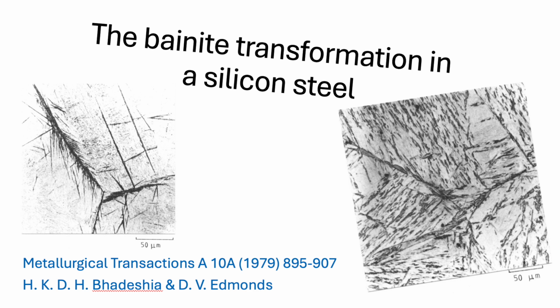And they found direct evidence for this supersaturation. Two really strong pieces of evidence. First, they occasionally observed mechanical twinning within the lower bainite ferrite laths. Twinning, that sounds pretty dramatic mechanically, like in martensite. Very similar to martensite twinning in this alloy, yes. It happens on specific crystallographic planes in ferrite. Twinning requires a very high internal stress or yield strength in the crystal.